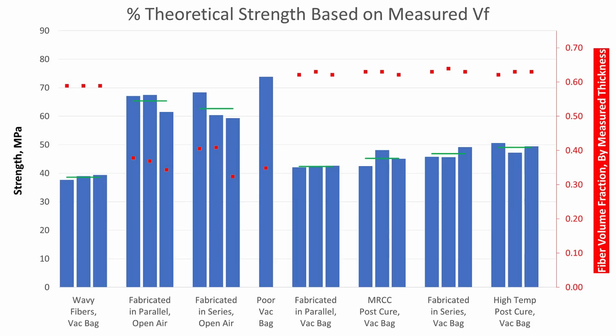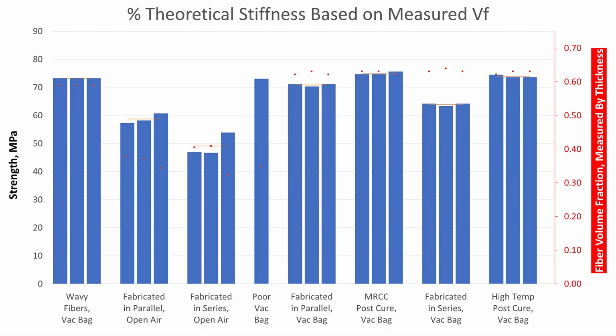Another result we can observe is that the difference between the expected strengths calculated by the fiber volume fractions and respective strengths of the fiber and resin is considerably higher than the achieved strengths of the samples. The differential is consistently larger for the vacuum-bagged samples, which achieved a higher fiber volume fraction and have a higher theoretical strength as a result. It is notable that this trend is reversed in the case of stiffness, with the open-air cured samples having a larger differential between theoretical and measured stiffnesses than vacuum-bagged ones. We will discuss a potential mechanism of this shortly.